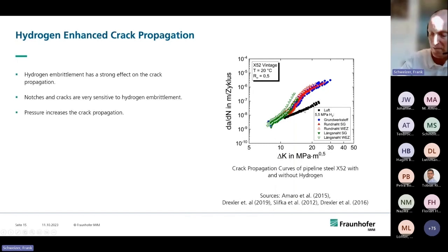The crack starts to grow faster and faster, and at the end of this, there's a catastrophic failure. But you don't see this in this diagram. And what you normally see in ferritic steels with hydrogen is that you don't have this linear relationship. You have an advancement of the crack propagation. So the crack grows much faster with hydrogen than with normal air.